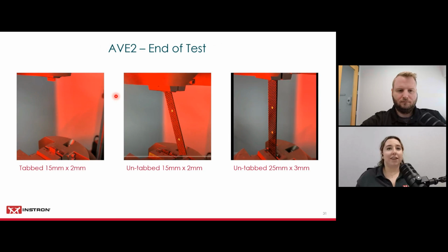For the end of test, again, my first tabbed specimen completely exploded, so we could see the leftover tabs within the jaw faces. My second specimen, the smaller untabbed one, had similar breaks as the one before, just outside of the jaw faces. And then my last one, it's a little hard to see, but it actually broke in the same location as it did with my clip-on test.